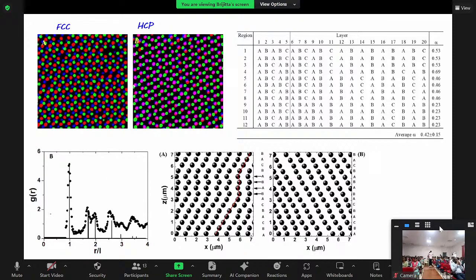Then if some physicists are there, they may know about pair correlation functions. The pair correlation function is nothing but if you have a particle at a given origin, how another particle is related. So the first position tells you about the nearest neighbors, and the second and the other peak positions tell how nicely your sample is arranged. So we see a lot of peaks coming up. This means the particles are arranged in long range order, and these two peaks match with that of our simulated data, and it implies that the particles predominantly exist in the hexagonal close packing state.